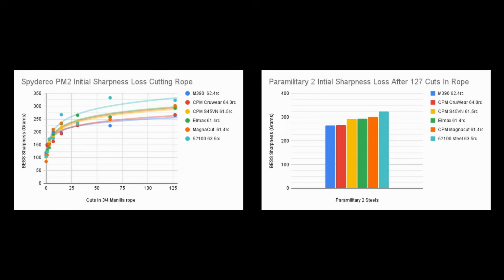This gives us an idea of how much extra edge retention you can get in a cutting scenario that sees high forces and therefore significant amounts of deformation at the edge. However, if the edge geometry of these knives was different, or if the forces were lower or higher in the cutting test chosen, the order of the knives could change drastically.